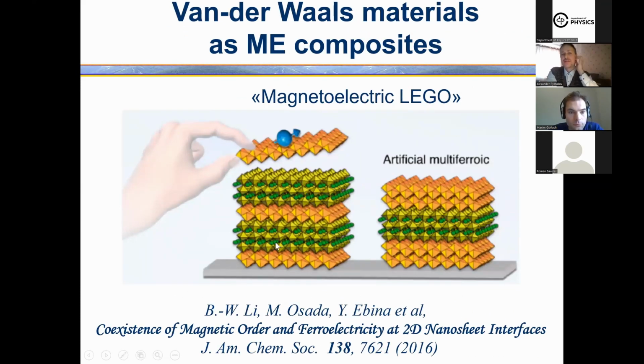So this field somehow should be fixed, and usually it is fixed by the substrate, and the substrate prevents deformation. But the recipe for it is to make some kind of columns of one phase in the matrix of another phase.